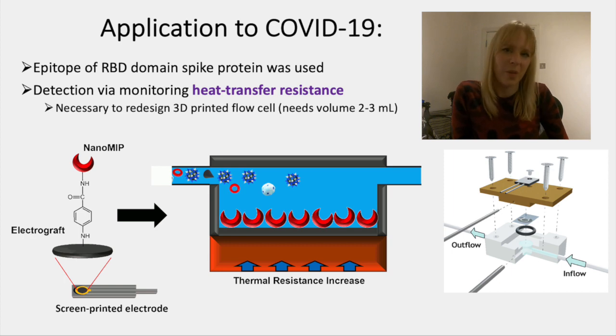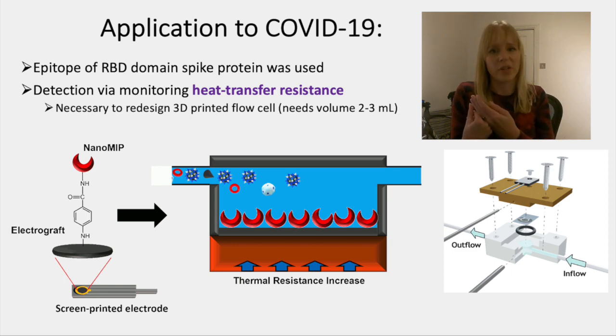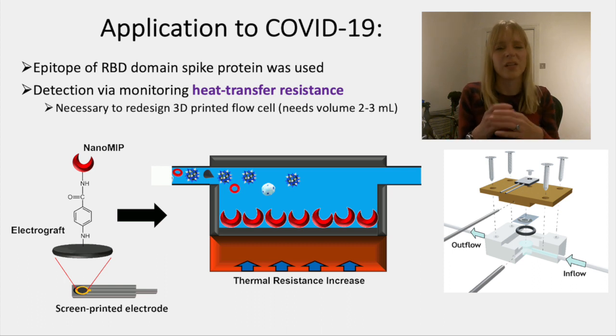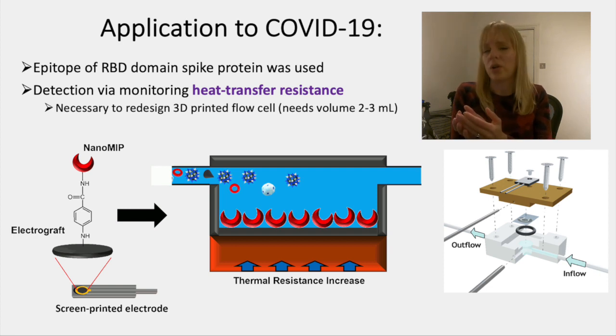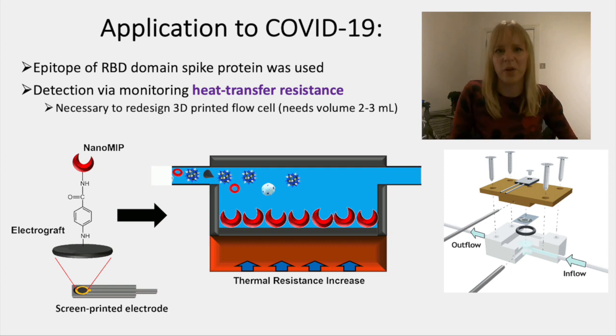But they use a specific epitope within the receptor binding domain. And that actually has advantages, even though we know there are lots of mutations that might occur in the receptor binding domain of the spike protein in general, because we only work with a very small fragment of it, that actually works to our advantage, because it's less likely that you'll have mutations within the short fragment, which is around 10 to 12 amino acids that was selected. The other advantage is that when you work with an epitope, it's much more stable and a lot lower in cost, so you can actually work with quite big quantities.